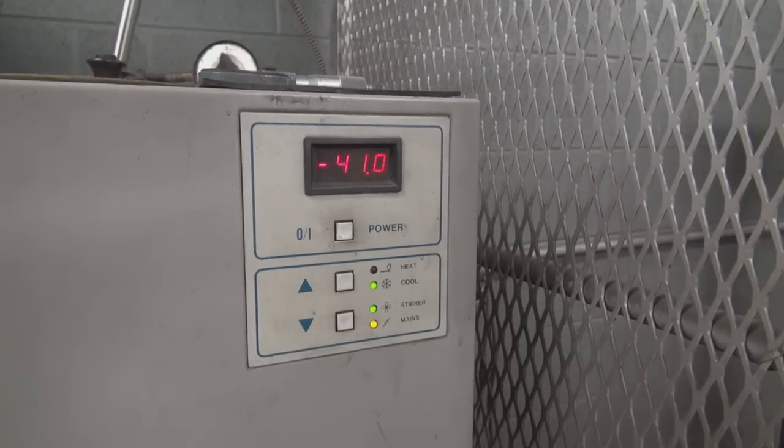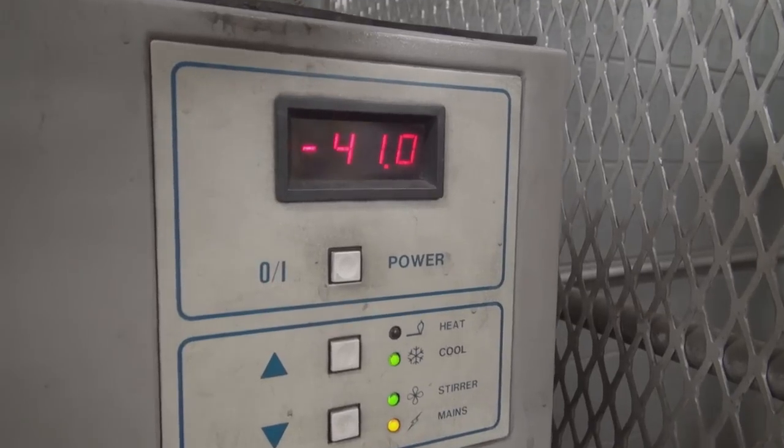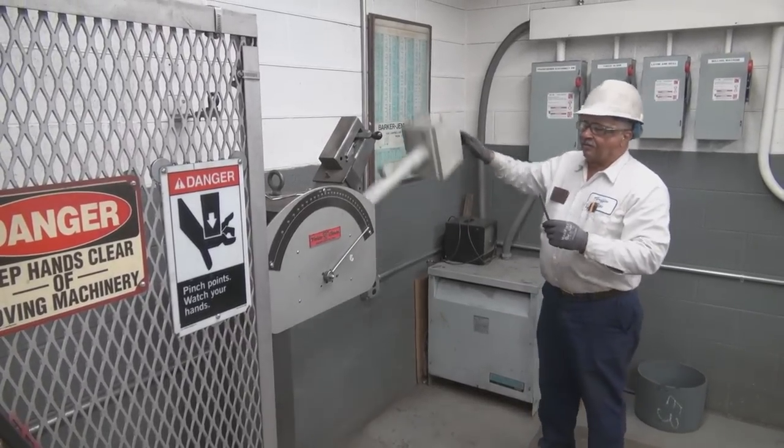One Charpy test must be run at -40 Fahrenheit to ensure that brittle fractures occur well below the expected temperature range experienced by ductile iron pipe. At this temperature, the sample should not break below 3 foot-pounds.